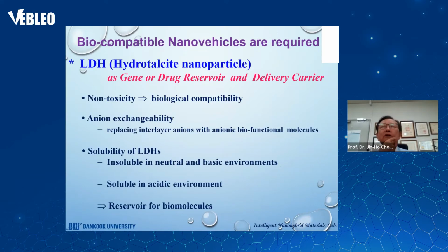According to the literature, layered double hydroxide is well known to be very biocompatible, and it has a very high anion exchange capacity, so that anionic drug molecules can be encapsulated into this lamellar structure, as I mentioned before. At the same time, layered double hydroxide is insoluble in neutral and basic environments. However, it is degradable in acidic solutions. That's why LDH is well applicable for drug delivery systems.